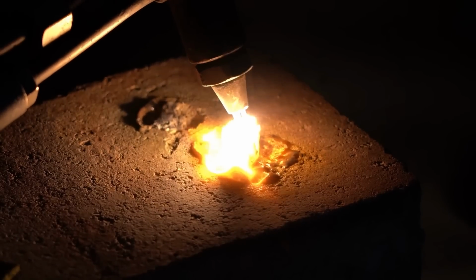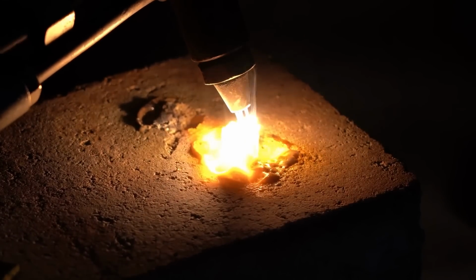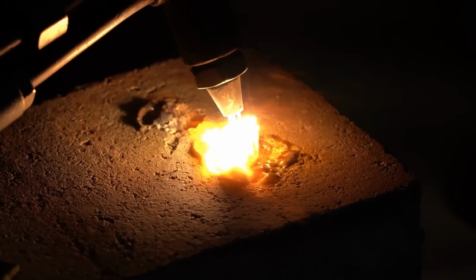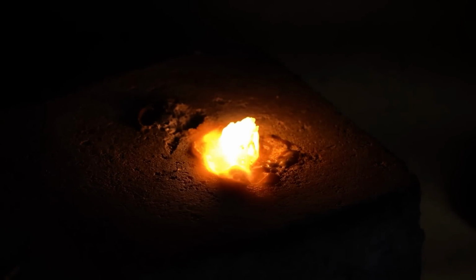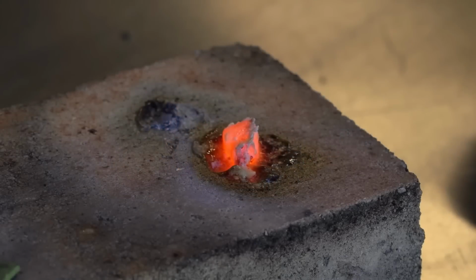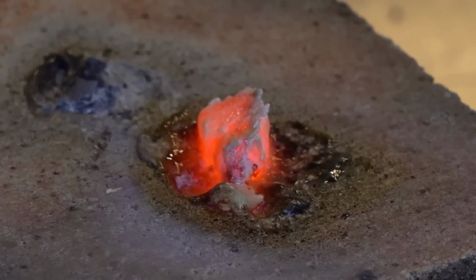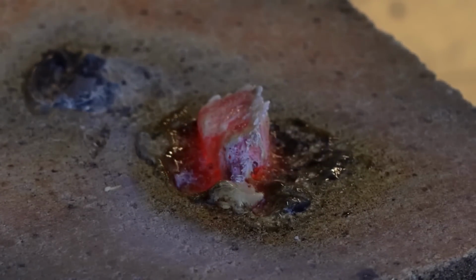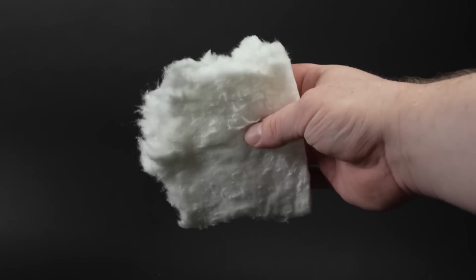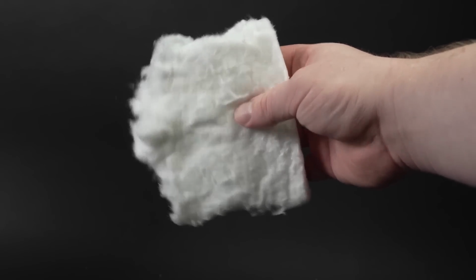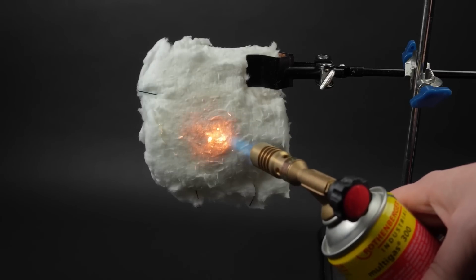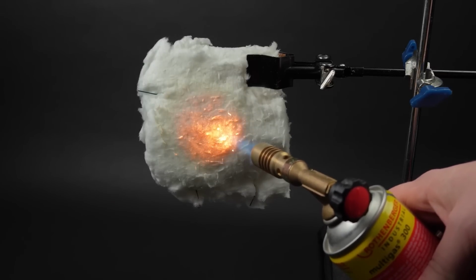However, under certain conditions it can still melt, as in one of my previous experiments. Here we tried to melt zirconium using an oxygen torch, but in the end, zirconium did not melt, while the fire brick underneath did start to flow a bit. However, fire bricks, although quite heat resistant, are also very heavy, so it is not possible to make rocket cladding from them. In addition to bricks, the store also sells what is called ceramic wool, which also withstands very high temperatures without melting or losing its properties.